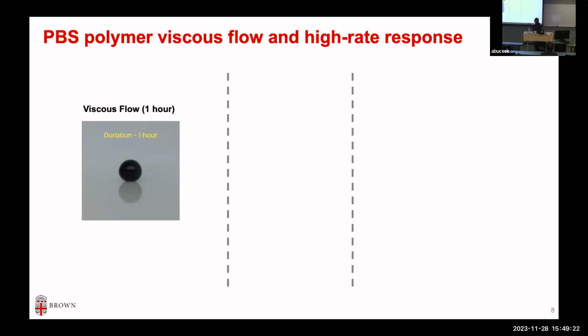So PBS is a short form for polyborosiloxane. What does this dynamic crosslink do? So when we make it, this is our own experiments now. If you make a sphere and put it on a table, it flows like a fluid. Just look at the 1 hour time scale, it will flow like a fluid. If you put it for a few hours in your pocket, it will go through between the threads of your clothing. So it's that fluid-like, except that the time scales instead of milliseconds are basically hours, right? It flows like a fluid.